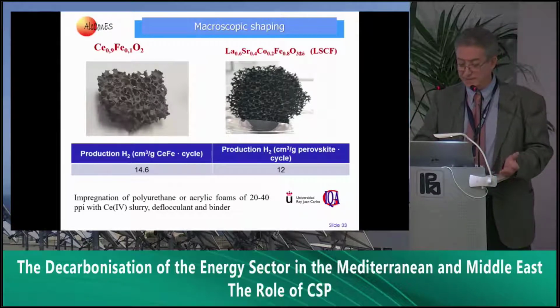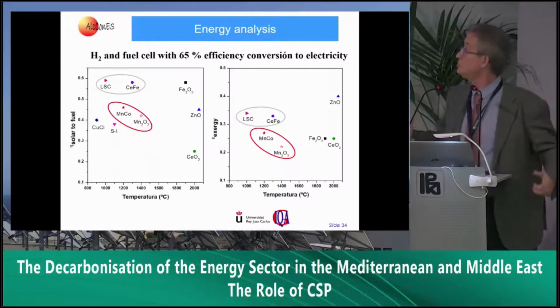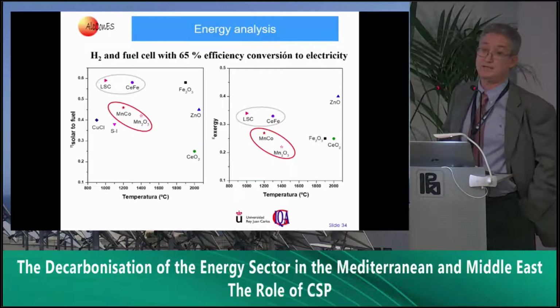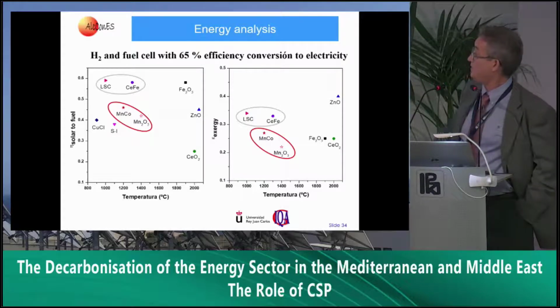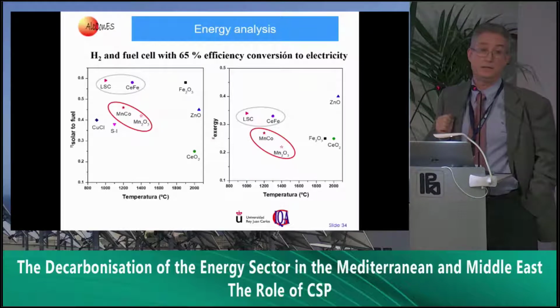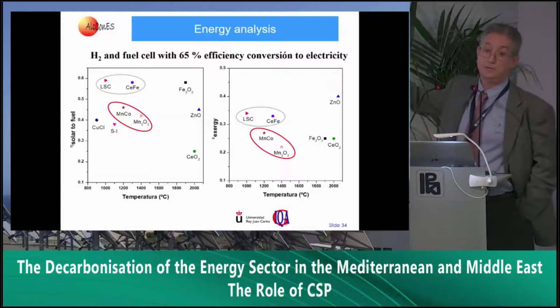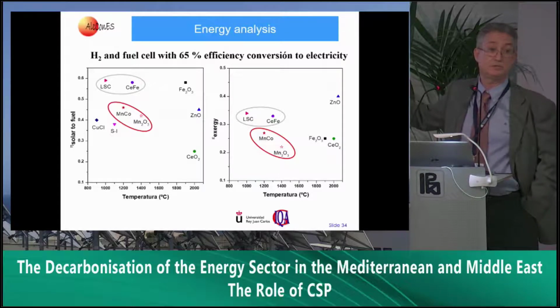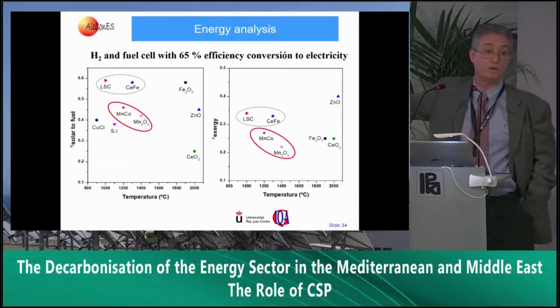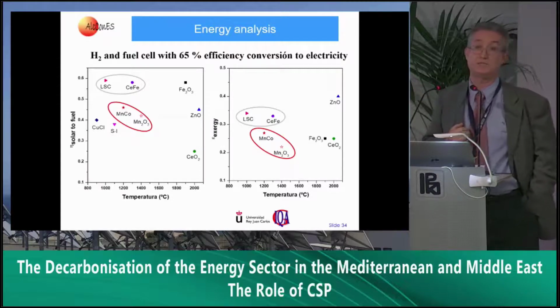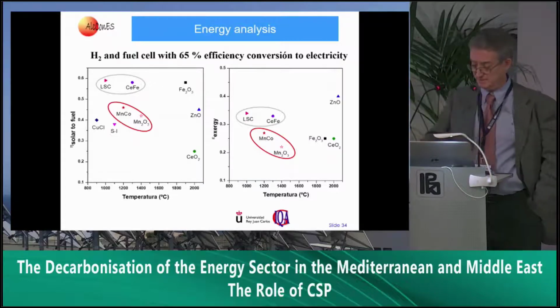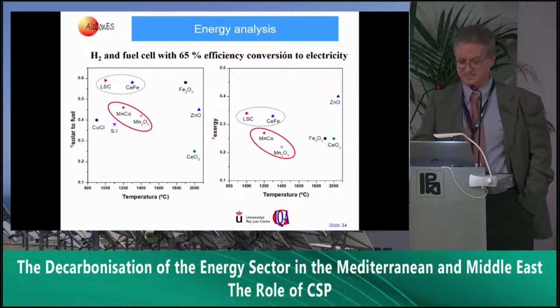And well, at the end, to summarize all these material solutions, we are always moving in this kind of graph where you have the temperature and the efficiency, and most of the efforts in the materials are trying to move from the complete stoichiometric oxidation reaction to the non-stoichiometric one on the left. You can reduce temperatures using, for example, mixed oxides or LSCF, which is perovskite. So at the end, that's basically the idea of the development of materials.